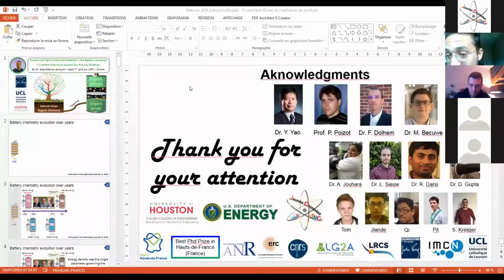But for the anionic one, the anions that we are using so far, because it's a lithium ion battery, nobody cares about the anion. We care only about the metal. So we use different anions, and the anions will change the solubility and the ionic conductivity. It plays a role in the electrolyte, but for this redox system, the anions that provide good ionic conductivity so far are high molecular weight. We are talking about 250 grams per mole. Usually we should consider this molecular weight in the calculation of the capacity. Most papers in the literature don't take it into consideration, and they show capacities which are already low because of the molecular weight of the molecule itself. If you add the molecular weight of the anion, it will decrease the capacity more.